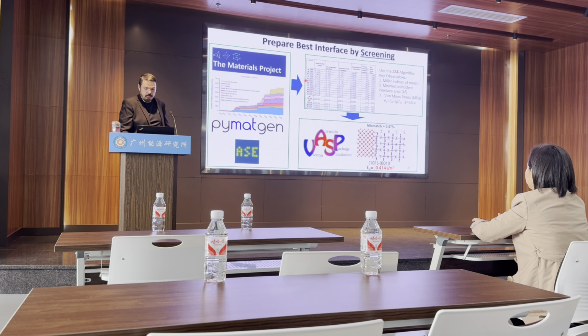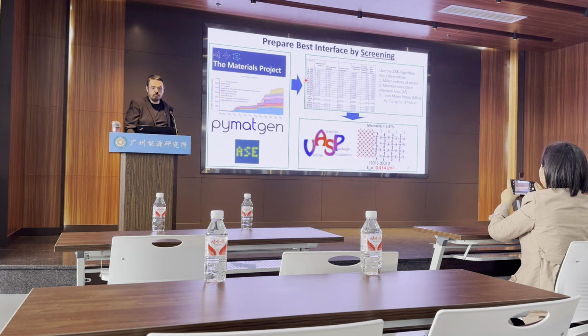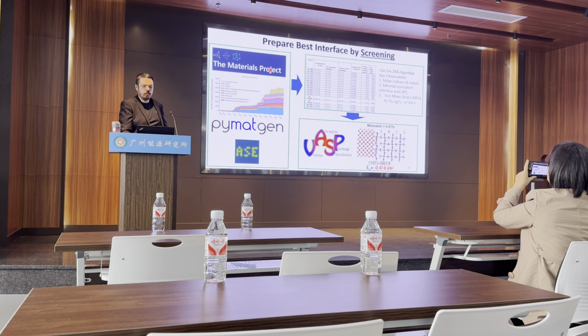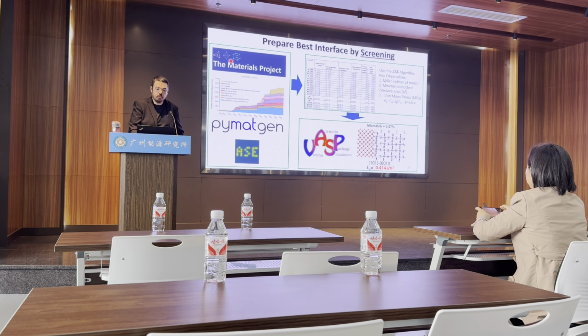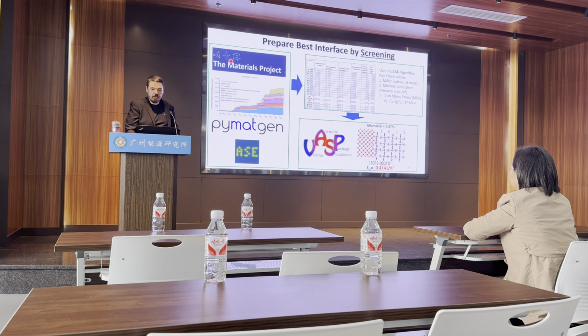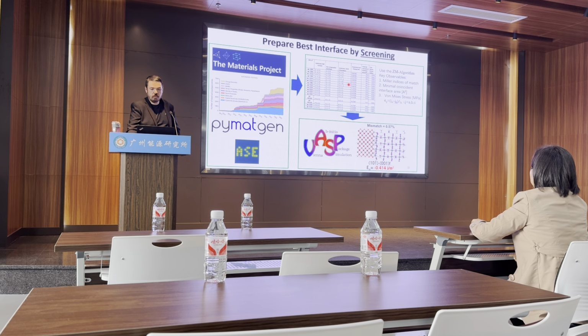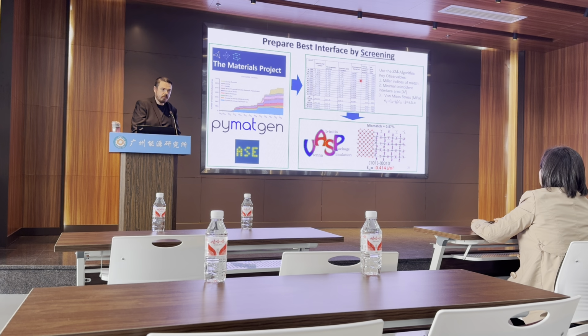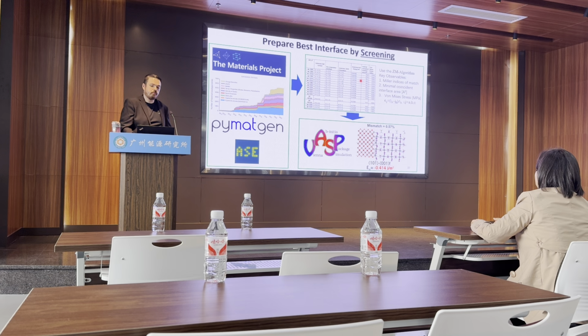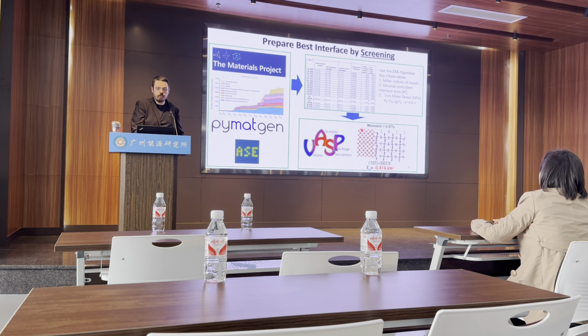So here's the work process. We take the Materials Project database, which gives us all we need. We find the minimum coincident areas and we tabulate them. And then we use experimental data to think about it. We just look at the XRDs. For example, for perovskite, we consider 100, 110. And then for the other material, we also look at the XRDs again. For example, zinc oxide has many different phases that are stable, so we also have to consider different phases of zinc oxide and the XRDs of each one.